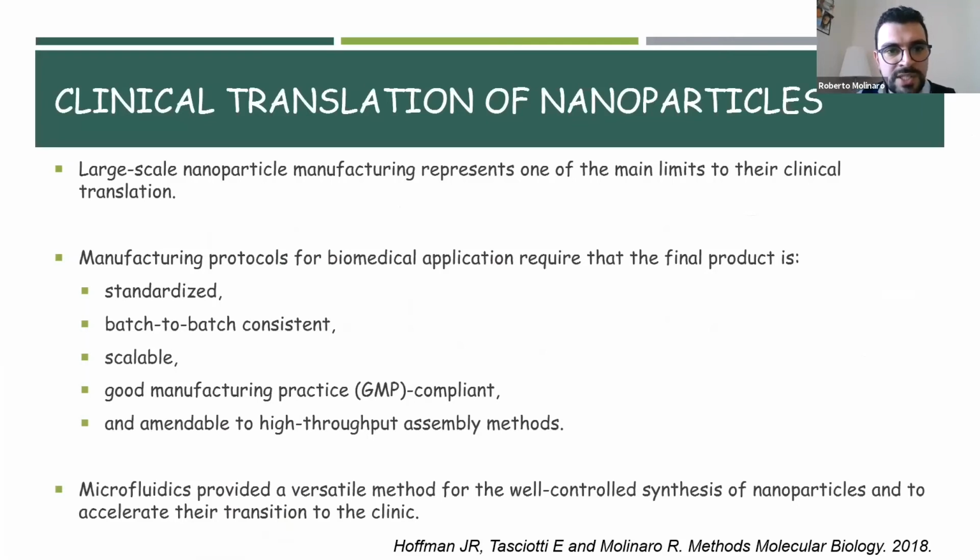And we know that large-scale nanoparticle manufacturing actually represents one of the main limits to their clinical translation. Manufacturing protocols for biomedical application require that the final product is standardized, batch-to-batch consistent, scalable, GMP compliant. And in the past years, we observed that microfluidics provided a versatile tool for the well-controlled synthesis of nanoparticles in order to accelerate the transition to the clinic.